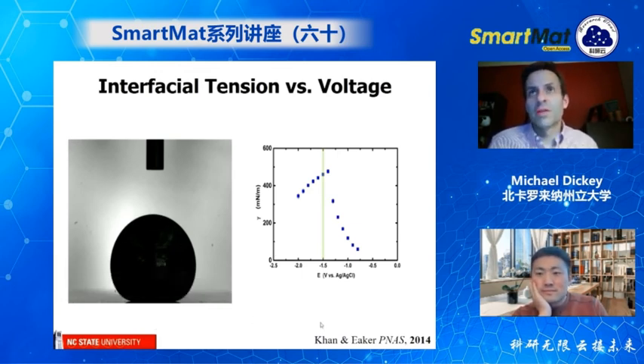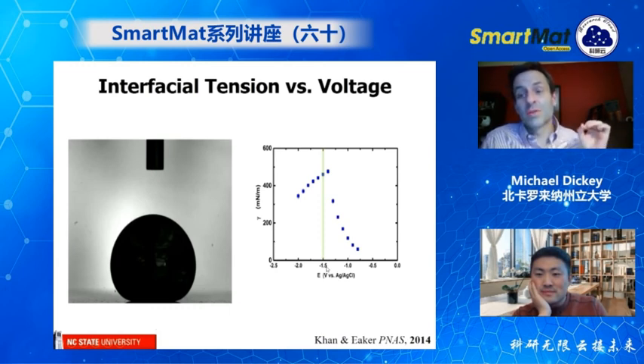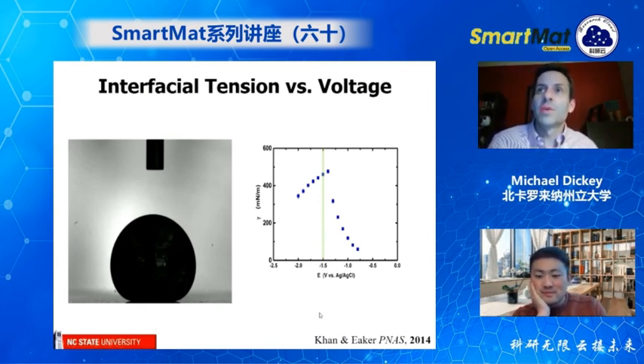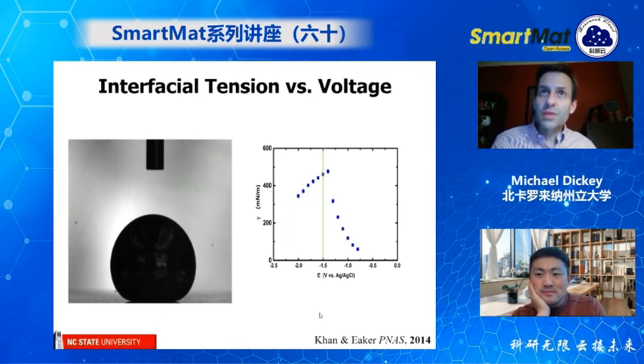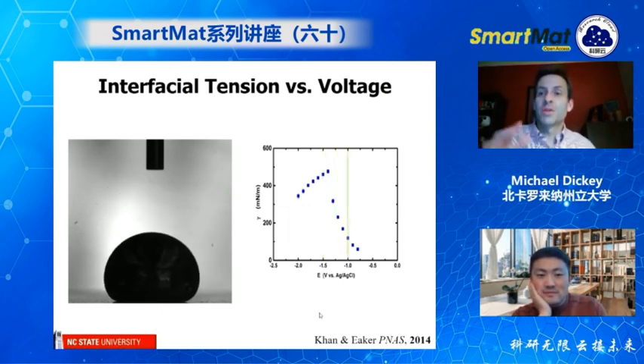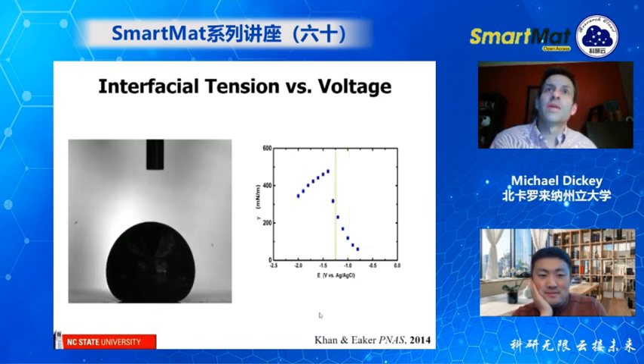Now, when we start applying the voltage, which again, remember we do from the bottom, you'll see it looks like we're applying negative 1.5, but this is actually 0. This is just what's called the open circuit voltage. So we're not applying any potential. It's just what happens when you stick the electrodes into the electrolyte. When we start the experiment, the droplet starts to squish some more. You see the tension gets lower and lower, and then it goes back, completely reversible.